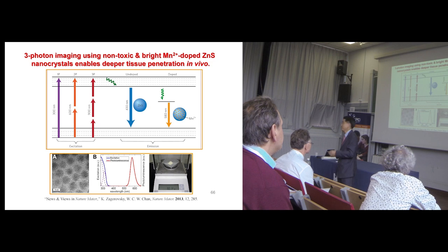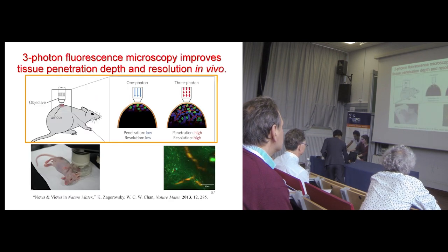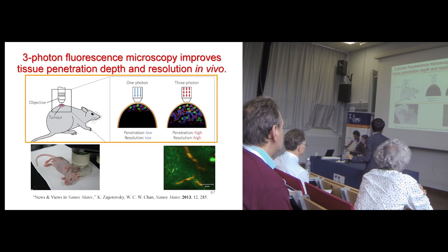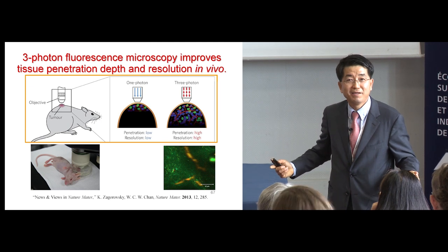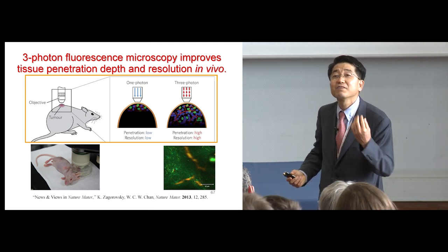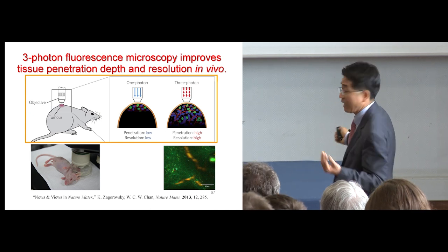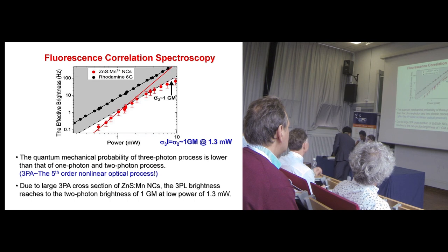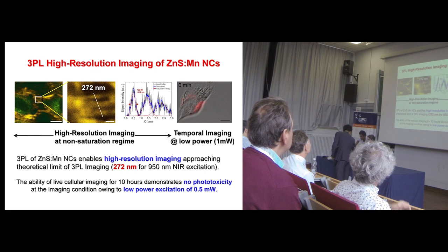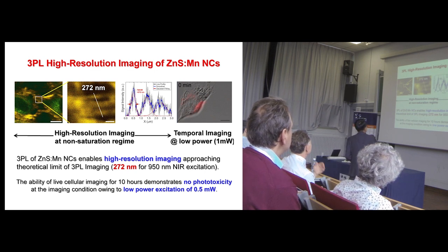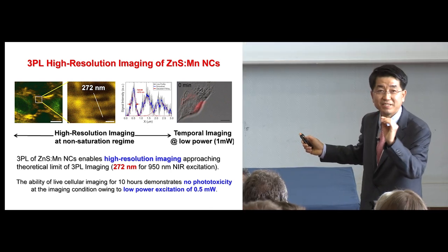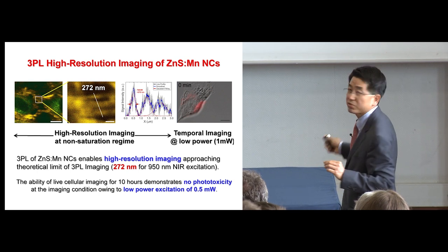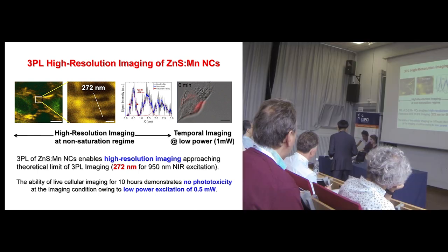And instead of one photon, we did 1, 2, 3-photon imaging for the first time in vivo. Because of the time limit, I just want to explain why we want 3-photon. By using 3-photon, we can have much higher penetration because we are using 950 nanometer NIR light. Resolution-wise, it should be a lot better than single photon or even 2-photon imaging. That's what theory calculated, and that's exactly what's happening. And then we showed that this is really 3-photon. Then we did cellular imaging, and we can see up to 10 hours of straight fluorescence imaging. Cellular level resolution of 270 nanometers can be resolved using this 3-photon imaging probe.